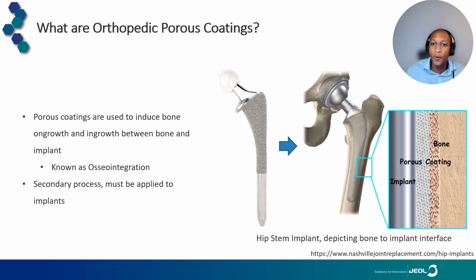And as you can see on the right, for example, we have a hip stem. And the hip stem, when implanted into the bone, you have that connection between the porous coating and the bone. So as you can imagine, where that implant sits inside the bone you see on the right, all that good bone needs to be removed in order to fit that implant in. And in order to get that implant in the bone to have good fusion between the two, that porous coating helps the bone grow into it and to be overall a part of the bone.